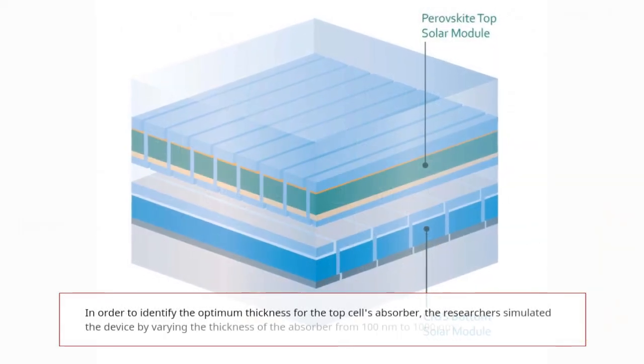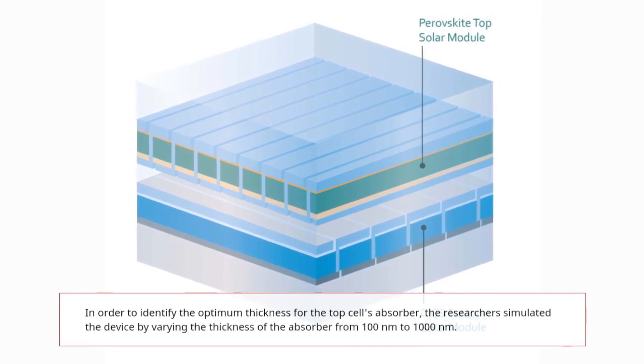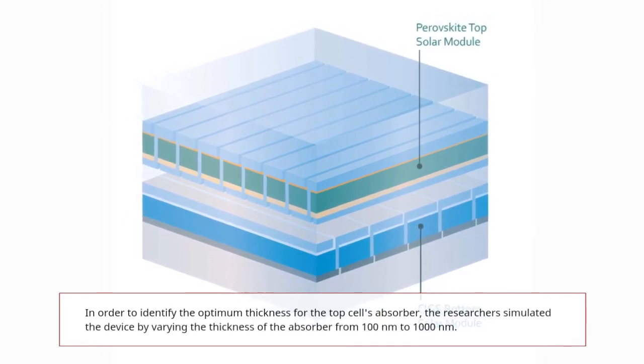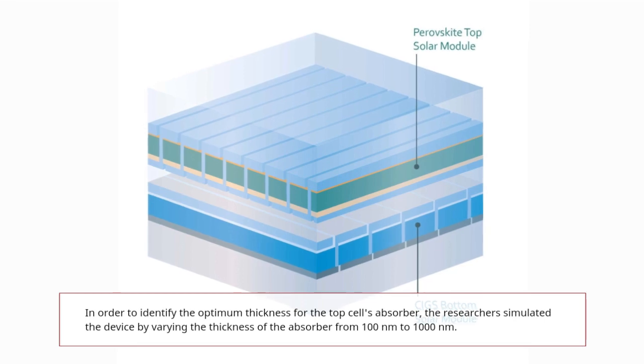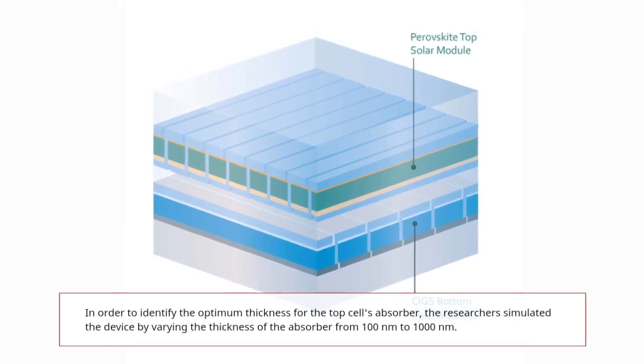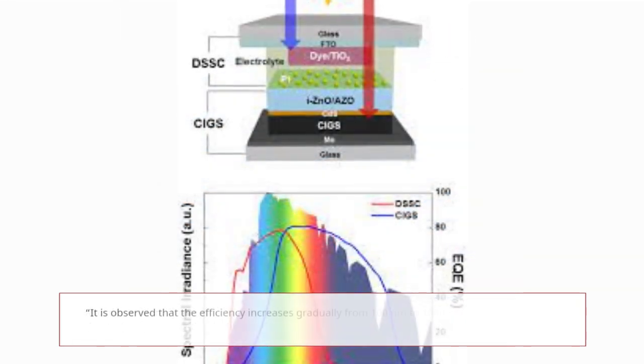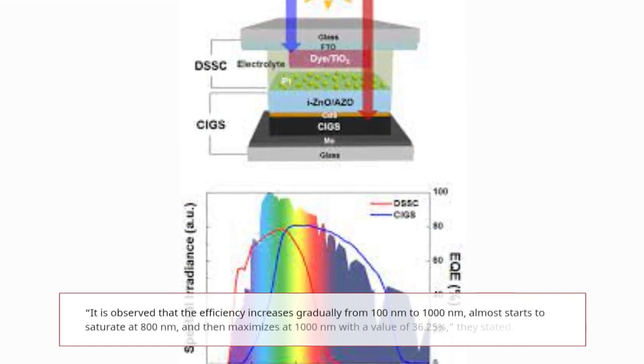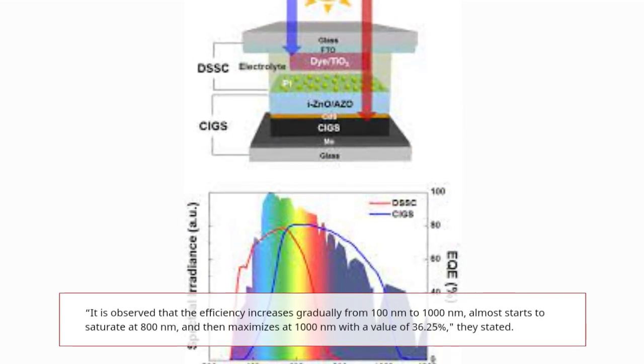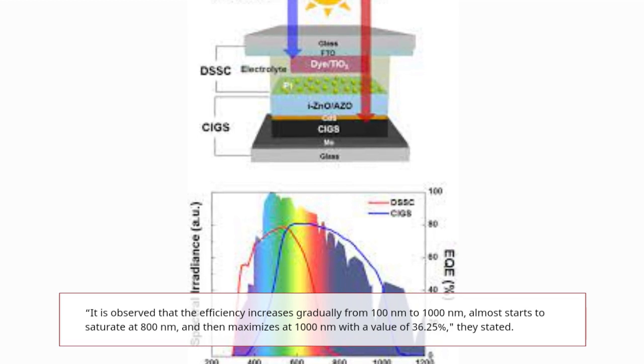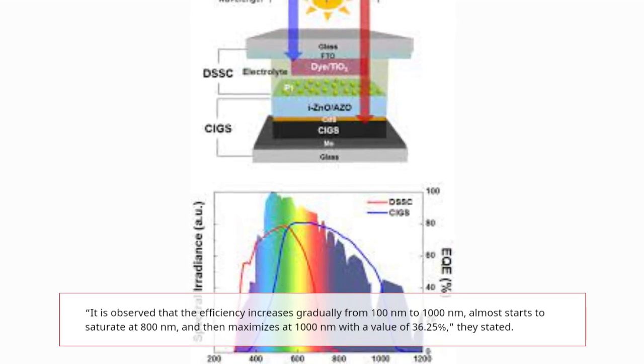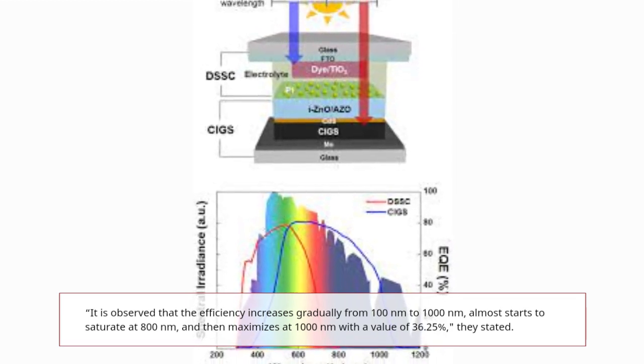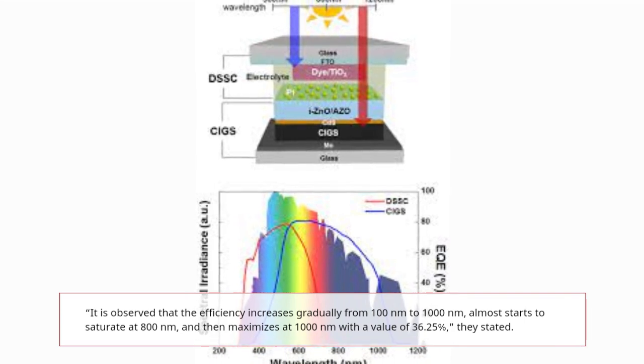In order to identify the optimum thickness for the top cell's absorber, the researchers simulated the device by varying the thickness of the absorber from 100 nanometers to 1000 nanometers. It is observed that the efficiency increases gradually from 100 nanometers to 1000 nanometers, almost starts to saturate at 800 nanometers, and then maximizes at 1000 nanometers with a value of 36.25%, they stated.